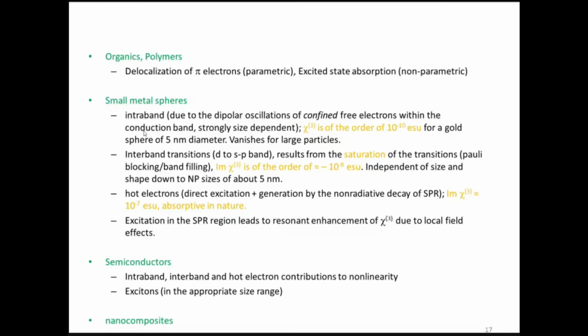So we know that in the case of a metal, the conduction band has many electrons there, and they are confined actually, so they can oscillate when there is electromagnetic radiation around. These free but bound electrons can oscillate, and they will have some chi3 because of that, of the order of 10 to the power 10 ESU for a gold nanoparticle of 5 nanometer diameter. But this will vanish for large particles, because when you come to large particles, the valence band and conduction band will all get mixed up, and therefore this bound electron picture becomes a bit blurred in the case of the metal lattice. So therefore, this doesn't exist for large particles or for bulk metal.